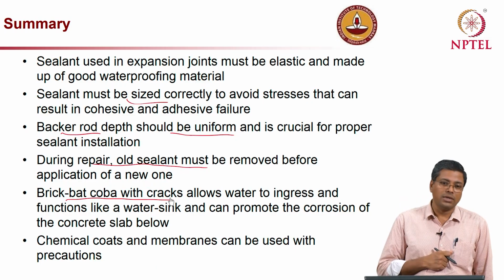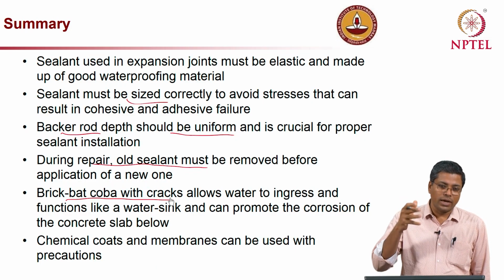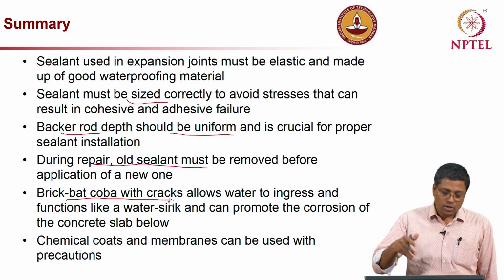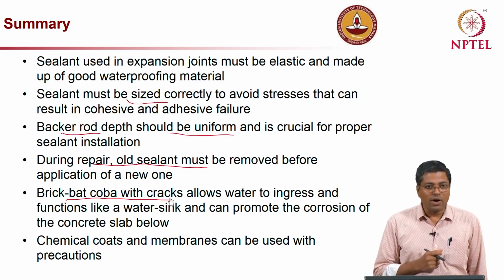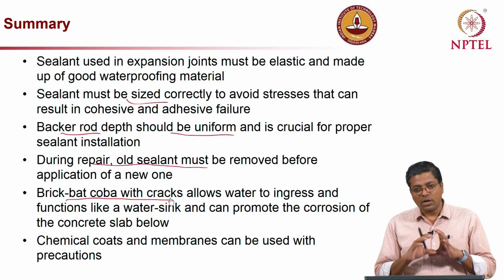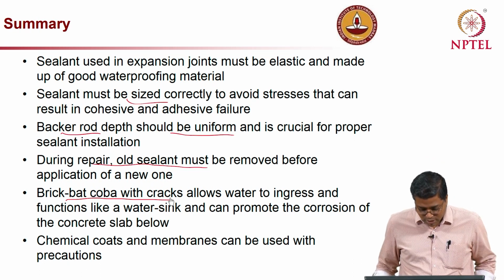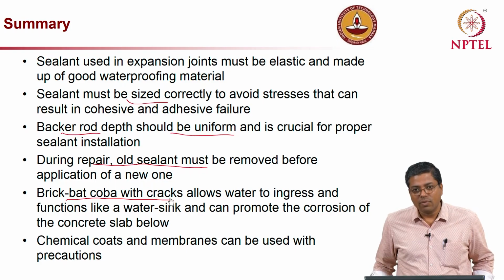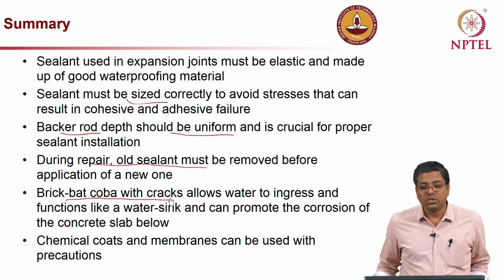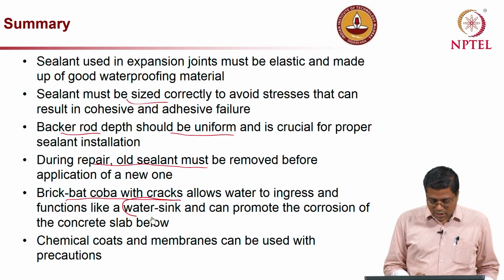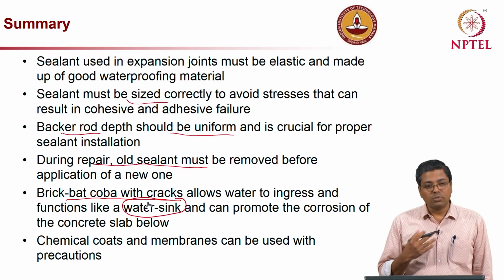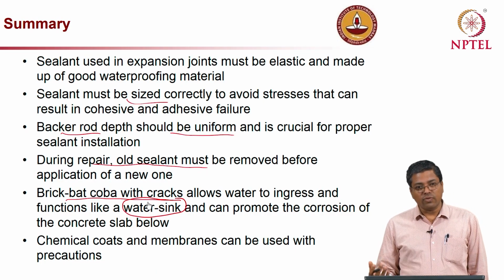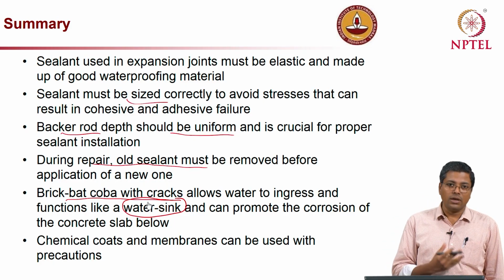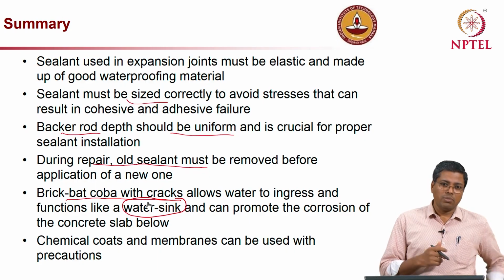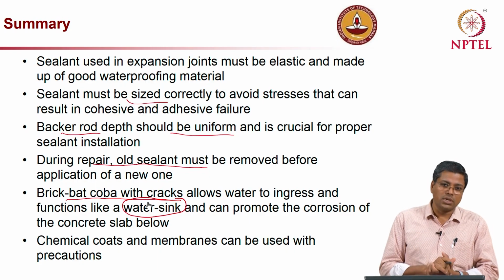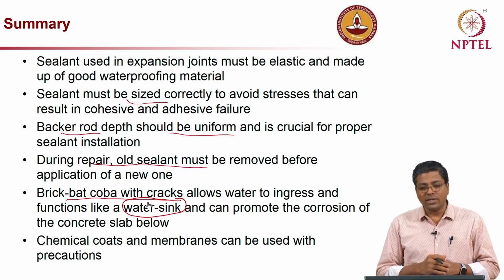And brickbat coba, we looked at what are the failure mechanisms. So, how the cracks can get initiated in the brick layer, and which will lead to the entry of moisture into the brickbat layer and into the brick layer, but at the same time it does not allow it to evaporate that fast, because of which the concrete roof below might have a significant amount of water, also it might get exposed to moisture for a long period of time. So, in other words they function like a water sink, the brick layer. So, it is better to avoid such systems. And also these brick layers, I did not tell this earlier, but they also add a lot of weight to the structure. Imagine that typically the brickbat coba will be about 6 inches at least, and they also add a lot of weight to the structure.